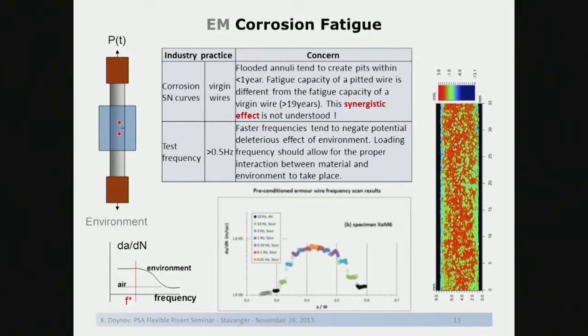So what you see here is the test samples, which is subjected to tensile tension, and we're introducing an EDM notch where we are trying to screen the testing frequency versus the crack growth rate, which is shown schematically here on this picture. So essentially, when we test in air, we can test at very high frequencies. However, when we test in environment, when we decrease the frequency, we're going to see that the crack growth rate is increasing, and it will do so until a point beyond which further decrease of the test frequency is not going to yield any change of the crack growth rate.